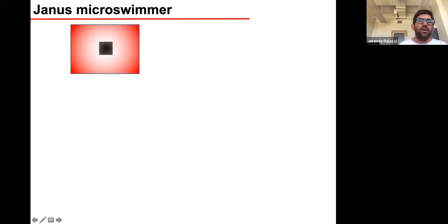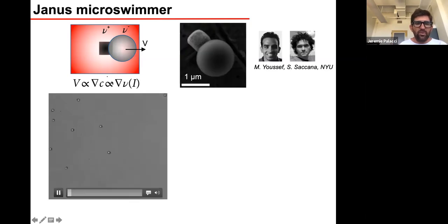So now we have this hematite cube, and we saw that if we put it in a gradient, it's going to move. But let's attach it to a sphere. The sphere, this polymer sphere, is inert. So we now have a particle which has a chemically active side and an inert side. We just remade a Janus, and it's a self-propelled particle. We know that the particles tend to travel towards a low reaction rate. So it's going to self-propel with the sphere heads on. That's what you can see here.